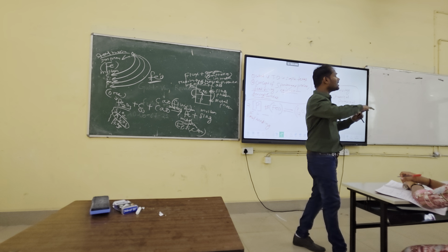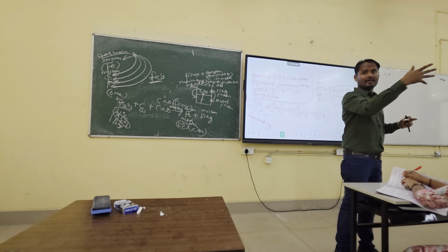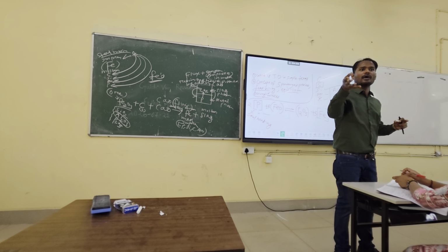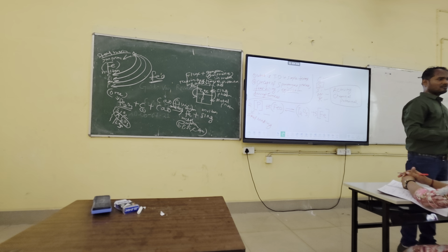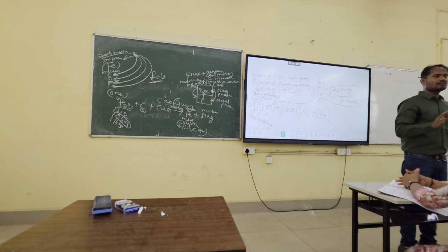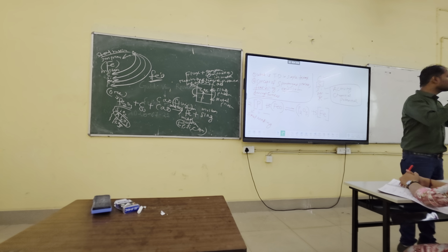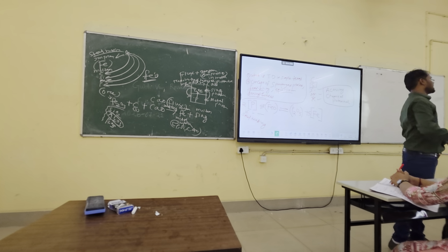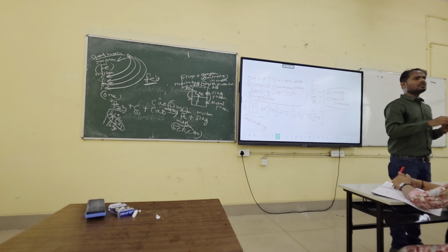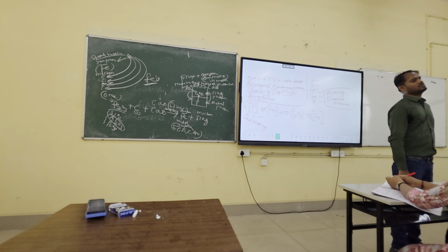But since the concentration of phosphorus is increasing in the slag, the activity of phosphorus will become higher in the slag phase. So it may come back into the metal by reduction. But you don't want that. You want your phosphorus to stay in the slag phase. So you are adding lime. Lime is a basic oxide. It will react with P2O5 to form a strong, stable compound. And the chemical potential or the activity will strongly reduce.